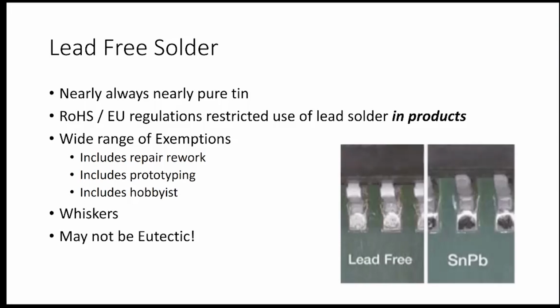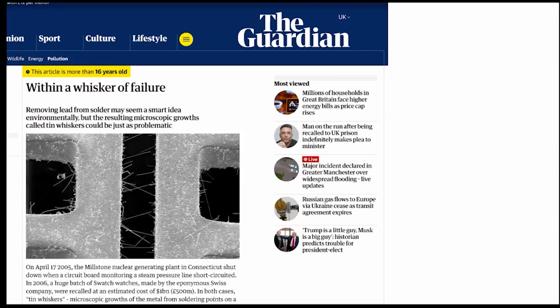And there's another thing that happens between crystals whereby if the thing is worked either mechanically or thermally, so you've got a piece of equipment, it gets hot, sunshine, it gets cold, dark, it gets hot, sunshine, it gets cold, dark. Then as these crystals flex a tiny submicroscopic amount, then whiskers of solder get exuded from the surface of it. And those whiskers can cause short circuits and can cause all sorts of damage.